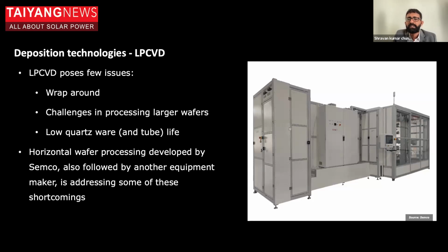And then there is also another challenge of processing the larger wafers in these LPCVD reactors, because when you are placing them back to back, during the dynamic processing environment in the reactor, during the heating up phase or cooling down phase, the wafer shakes slightly, vibrates. So then there is also a chance for breakage.